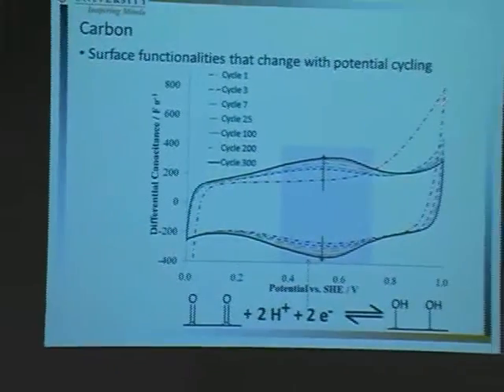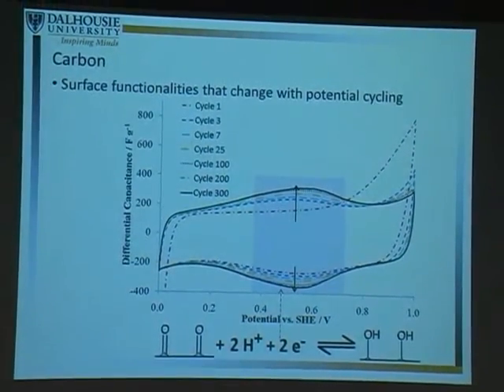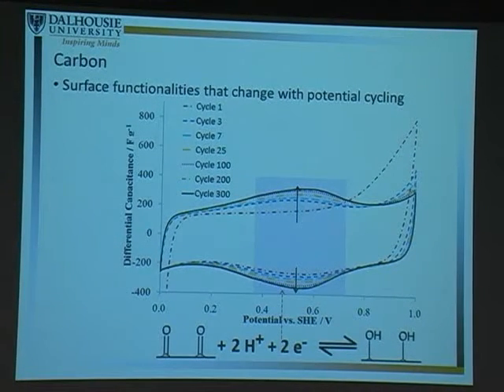So we've seen this CV already, but let me now explain what we see here. If you take your carbon, put it in sulfuric acid, and you run the CV, this red one is the first one you will see. And you see that in this region there's no charge storage, there's none of that pseudocapacitance. But as we take this carbon and we cycle it in sulfuric acid for about 350 cycles, which takes about a week to do, we can develop these quinone peaks. So this is the quinone-hydroquinone reaction. This is a pseudocapacitive reaction. It stores more charge for us. The other reason we use this is because we believe that these surface functionalities actually cause self-discharge. So we wanted a carbon where we had a very clear electrochemical signature for the surface functionalities. And we see that with this carbon, and I'll talk a little bit more about that later.